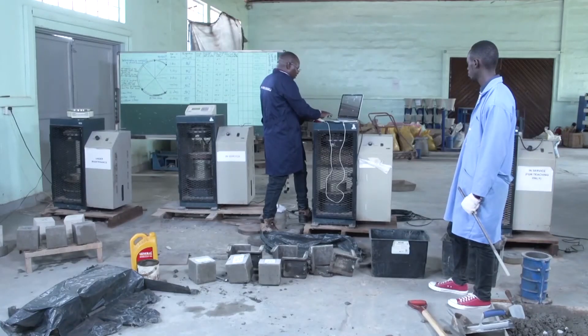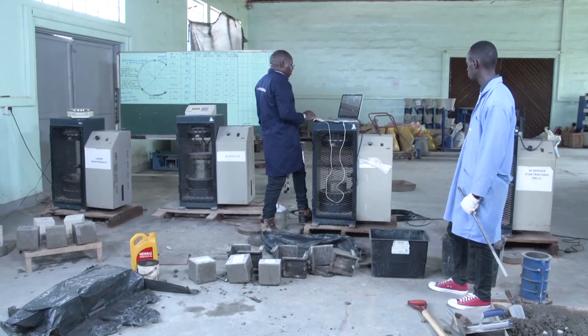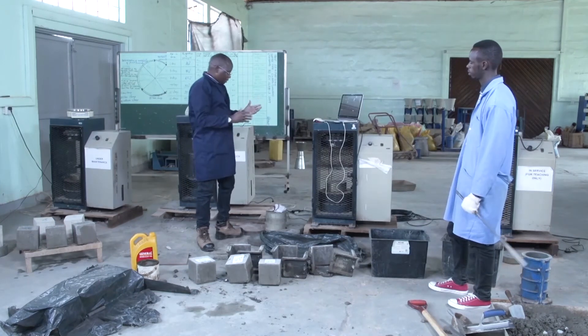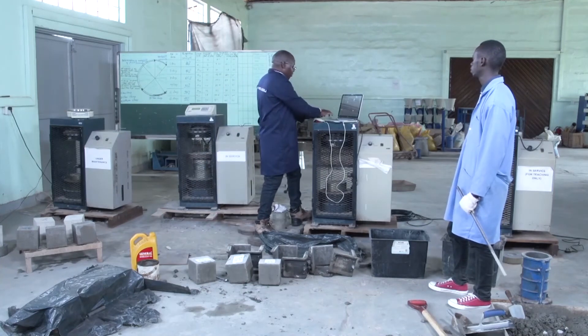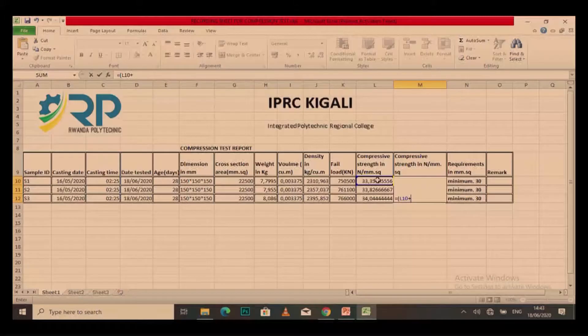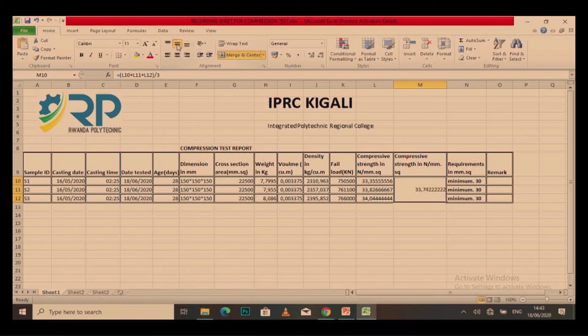For sample number 3, I take its load divided by its area, which equals 34.0. From here, I have three samples and I need to make the average. The average is equal to the value of sample 1 plus sample 2 plus sample 3, divided by three. I get an average compressive strength of 33.7 N/mm².